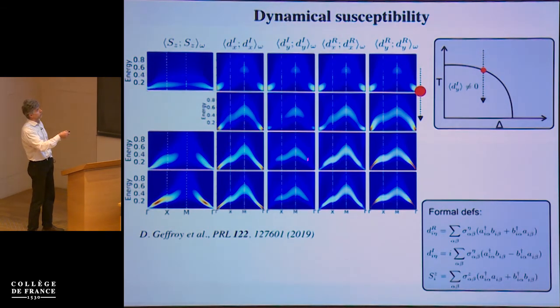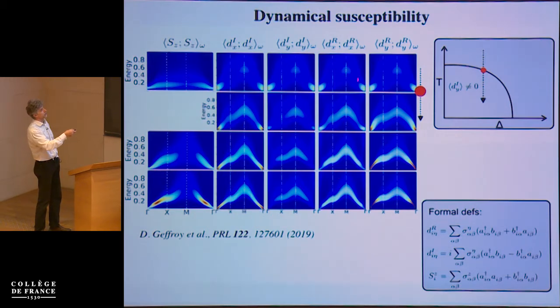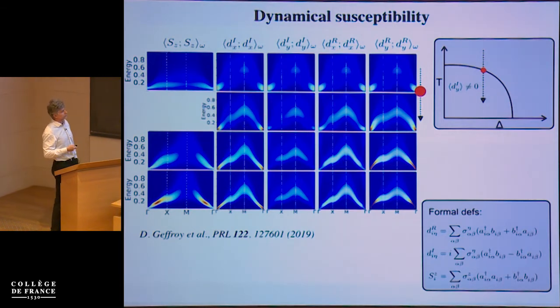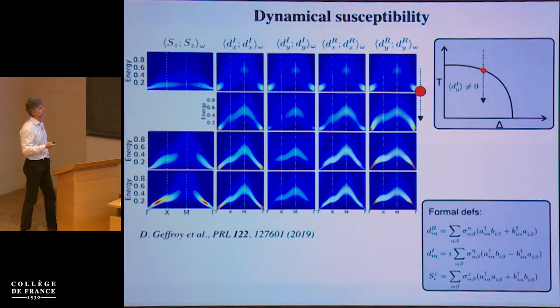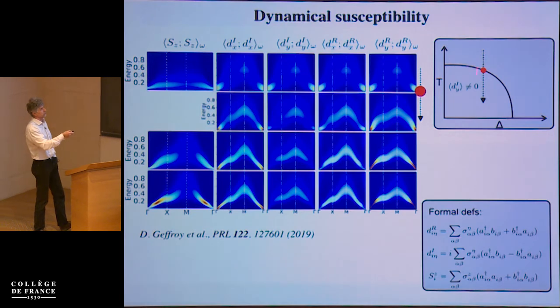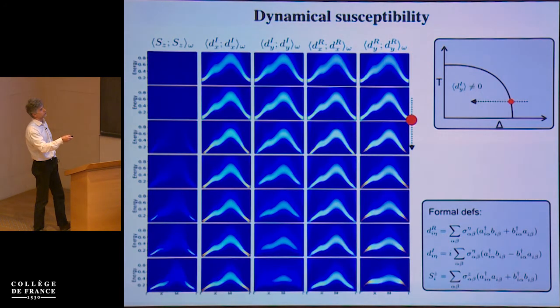When we cool down to the ordered phase, you can see this development of some linear modes, and the symmetry of these susceptibilities is broken. Perhaps the more instructive way to look at this is not the temperature-driven phase transition, but the transition driven by changing the crystal field.